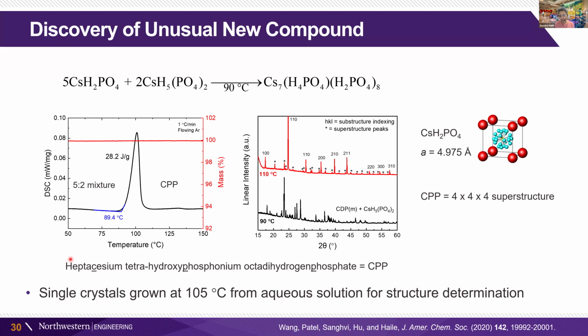And as you look at the in situ X-ray diffraction results here, you can see that at room temperature, we have a mixture of those two precursors. Then as we go to 110 degrees Celsius, we get a pattern that looks very similar to our cubic cesium dihydrogen phosphate pattern, but it has a number of superstructure peaks. And we also see in the DSC plot that there's a transition to this new phase. Okay, great. So we have this 4x4x4 superstructure that we can index.